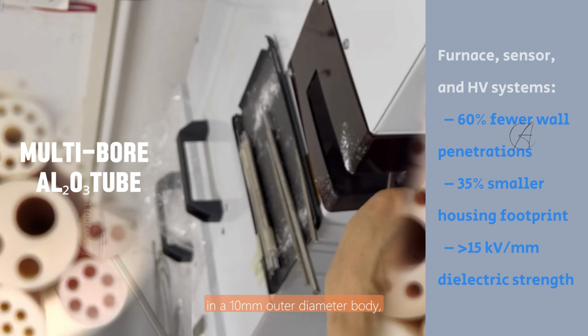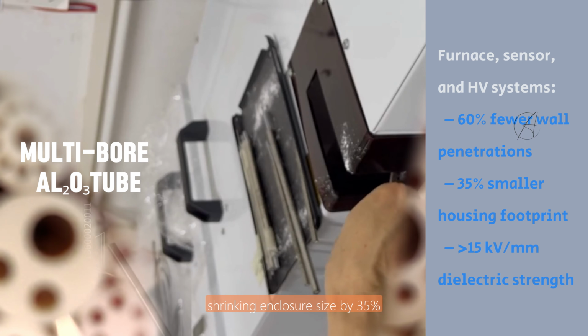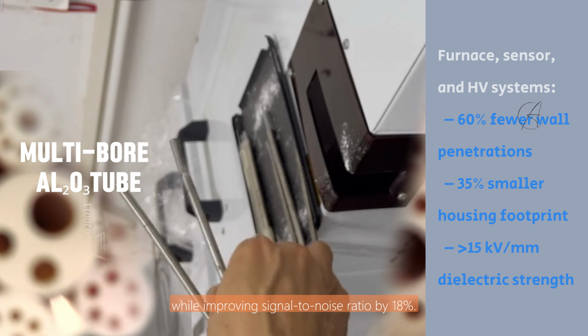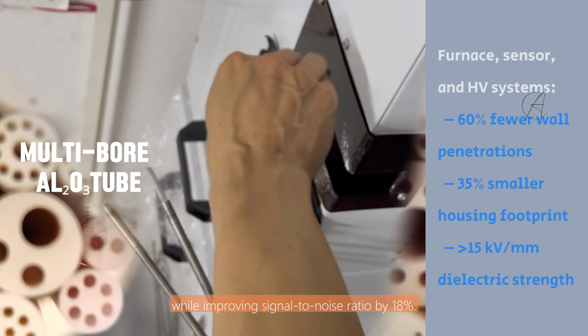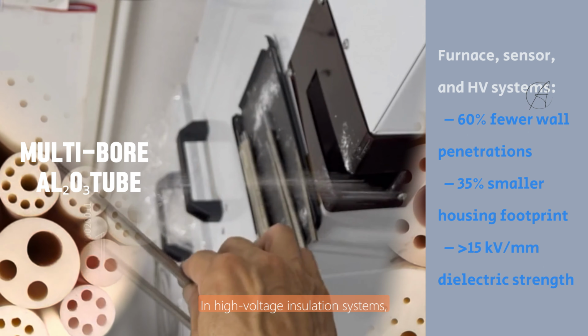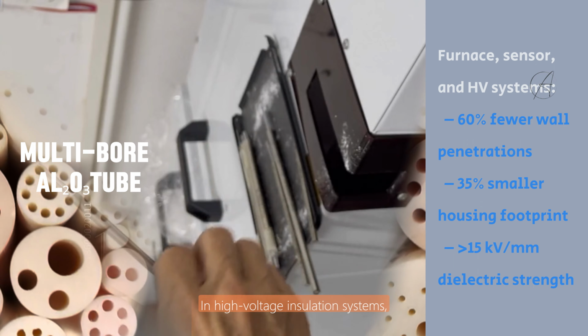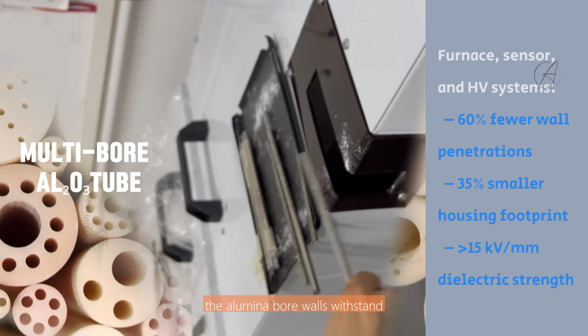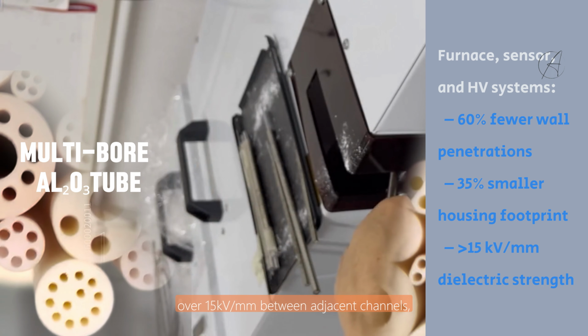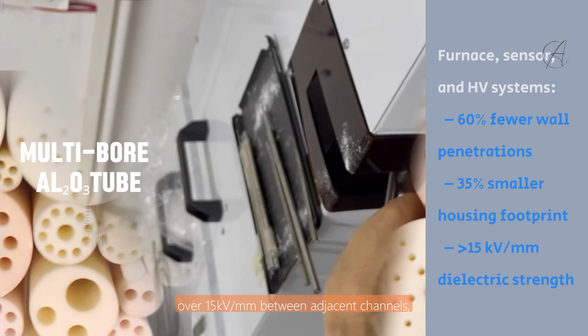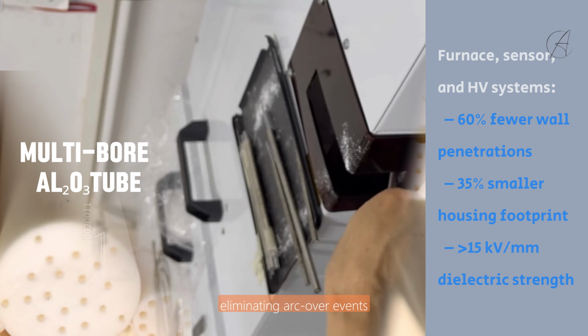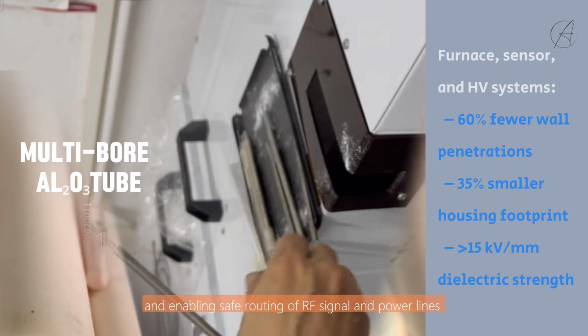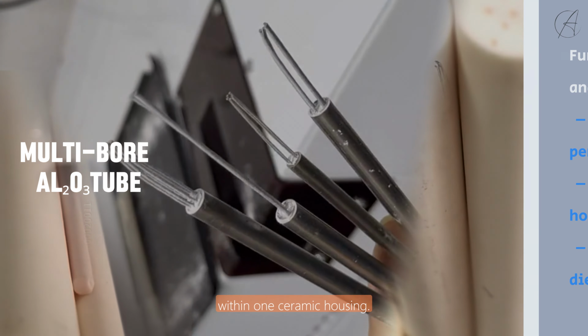outer diameter body, shrinking enclosure size by 35% while improving signal-to-noise ratio by 18%. In high-voltage insulation systems, the alumina bore walls withstand over 15 kilovolts per millimeter between adjacent channels, eliminating arc-over events and enabling safe routing of RF signal and power lines within one ceramic housing.